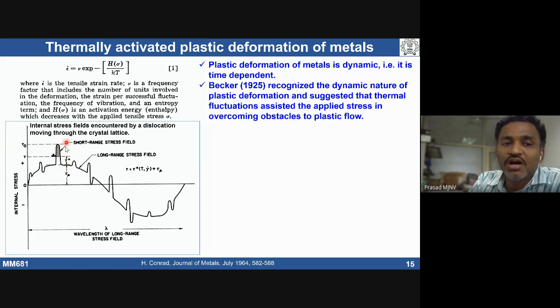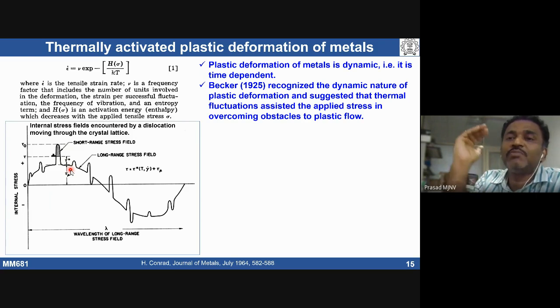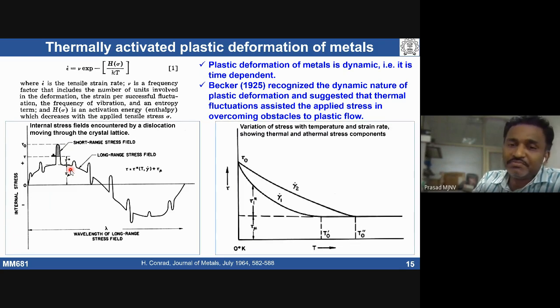And tau star is the stress required to overcome thermal barriers. That means the total stress required, tau naught, is equal to tau mu plus tau star at any given temperature. At any given temperature, the total stress required to initiate plastic deformation, plastic flow in the material, I need to apply tau naught. That is equivalent to the stress to overcome the athermal barriers plus the stress to overcome the thermal barriers.